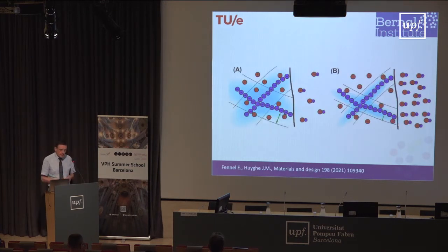Now, things are kind of complicated also in terms of material properties. We've done detailed experiments on this, and MIT has also done experiments on this in cartilage. If you disallow cartilage to swell and change the salt concentration within which it resides, you will find that the cartilage is going to stiffen as the salt concentration goes down.